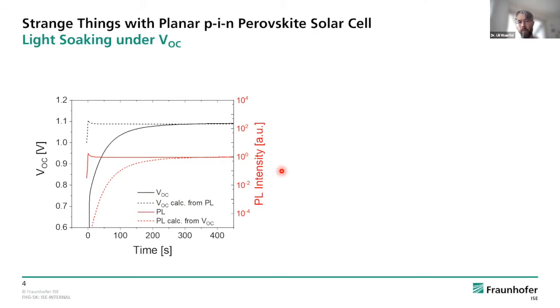So somehow we observe here two strange things. First of all, the open circuit voltage starts at a really low value, but then over, let's say, some hundreds of seconds, reaches a good value of close to 1.1 volt. For these kinds of solar cells, it was a good value. And second, there seems to be decoupling, because the photoluminescence rises very steeply in the beginning, but then stays constant.